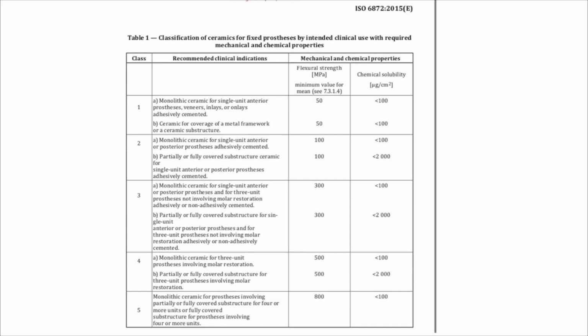So if you look at classification 4, you have a lot of the Emax, Sapphire, and glass ceramic crowns. They're very close to the strength of some of the 5Y zirconia without the chances of it getting weaker once you air abrade it. So you have to really think of what it is you want to put in someone's mouths.